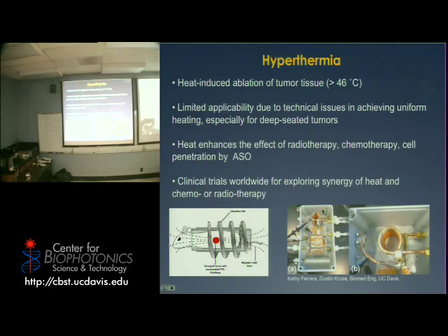And if there are particles in there, they heat up. And if you remember the slide before, where it says that radio frequencies usually go through the body, no problem. If the magnetic field is modulated in the radio frequencies, your body is okay, but the particles will heat up. All right, and you can use microwaves, and you can use radio frequencies for doing this type of thing.